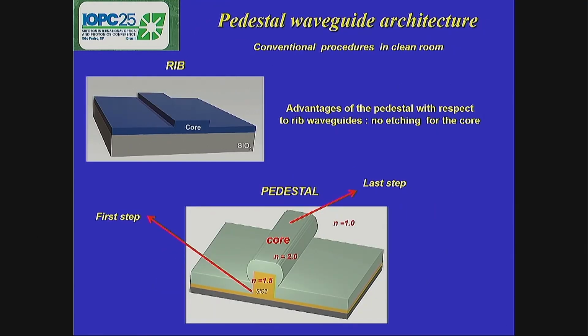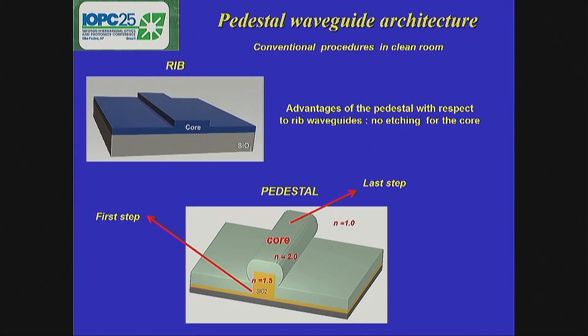There are many architectures that we use to produce these waveguides. At the beginning, we used the rib architecture, but in this case, we have a disadvantage because we have to etch the material of the core. It's not that easy to etch heavy metal oxide materials. Normally, they are inert to etching procedures.